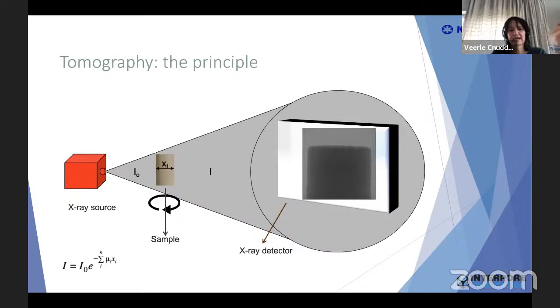What you measure as intensity in your detector depends on the intensity coming out of your X-ray source, and then depends on the interaction of the X-rays with your material. This is depending on the sample size, so the thicker your material and the longer the X-rays need to penetrate, the less intensity will come out.